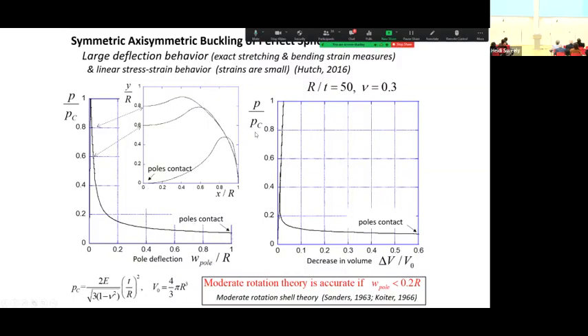This is the corresponding plot of the pressure normalized by the buckling pressure of the perfect shell and the decrease in volume of the shell divided by the volume of a full sphere. And the poles come into contact at the point where the volume loss is about 60% of the total volume. That's way beyond anything we're interested in. But this demonstrates just how incredibly nonlinear the post-buckling behavior of these shells is.